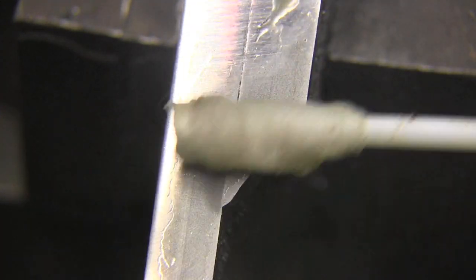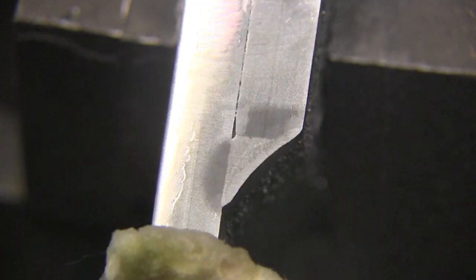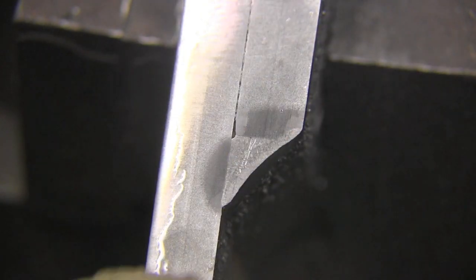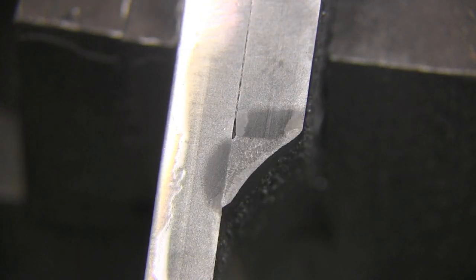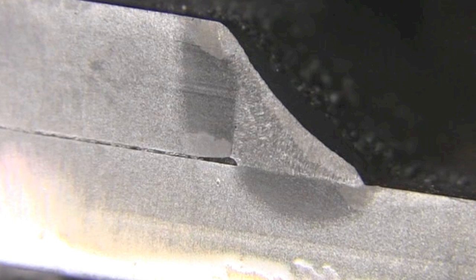Not a lot of depth of penetration there. That's very surprising. Even though the metal was nice and clean, down to bright metal, and that acid etch reveals that weld metal, while it may have fused, it may have actually bonded, it just didn't get any depth of penetration at all. It looks almost like a brazed joint.